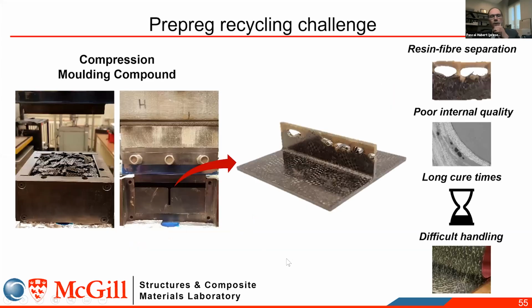So let's say that you want to do it without doing all of what I'm going to present. You're just going to take the offcuts, cut them, and try to make a part through compression molding. You're going to get an ugly part. You're going to get resin and fiber bleed, very poor quality with voids. It's going to take a long time to cure that material. And the material is going to be very hard to handle because you're dealing with a pre-preg that is tacky because it's straight from the roll.